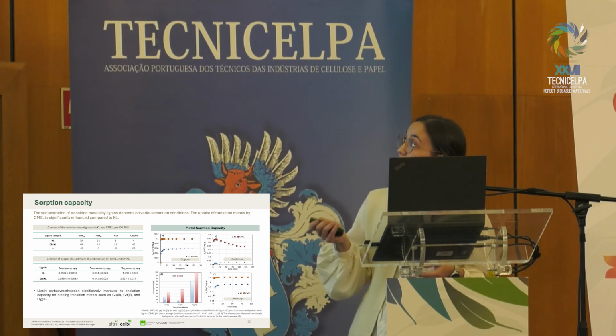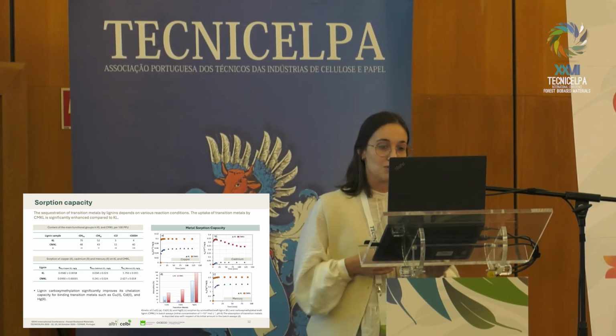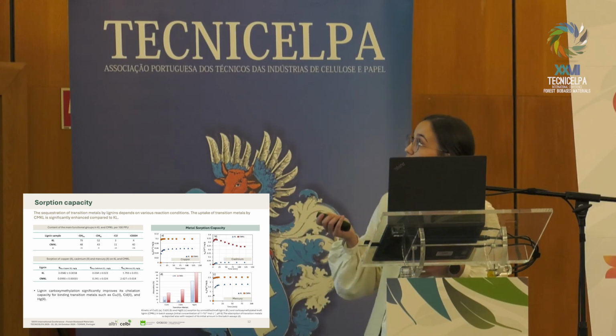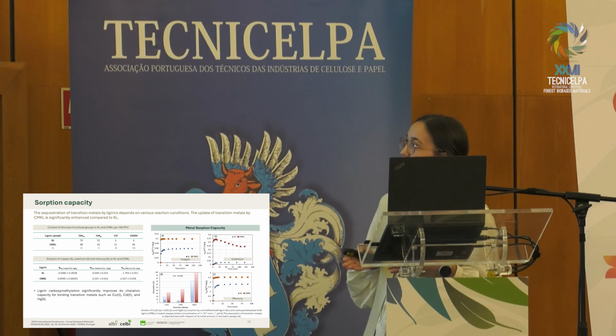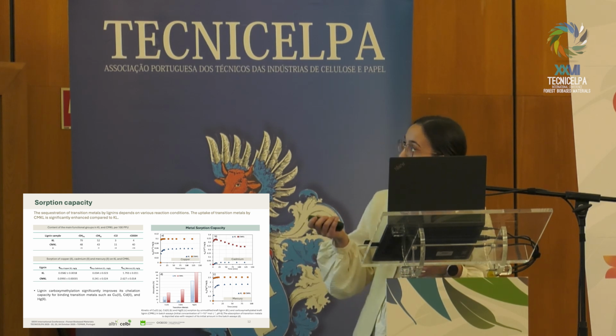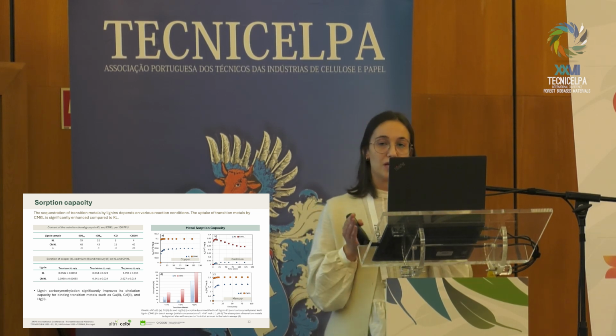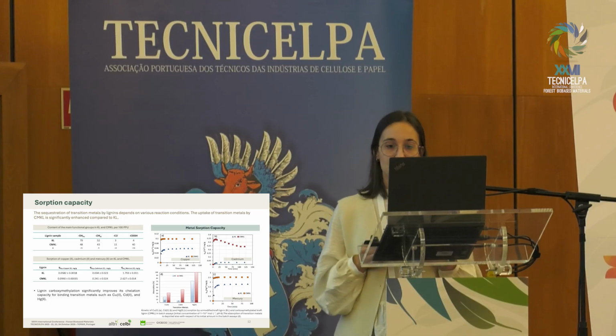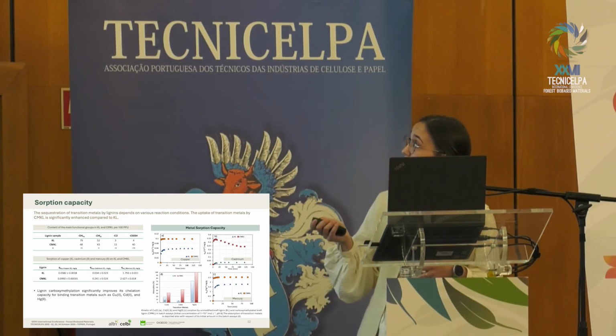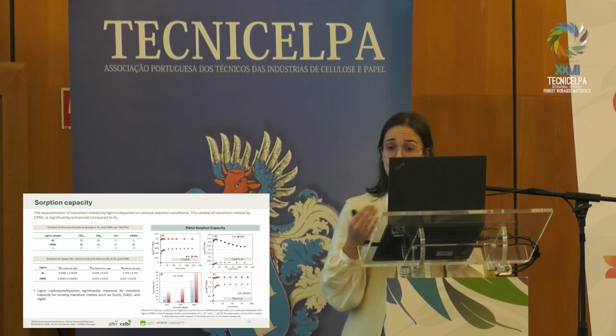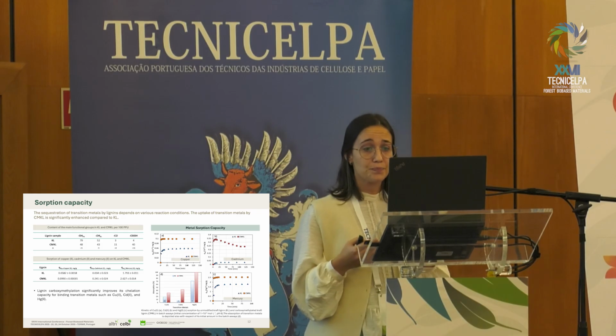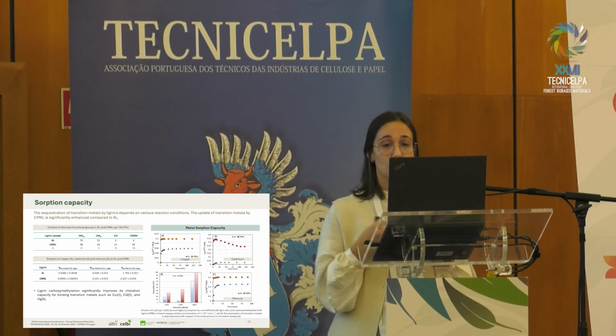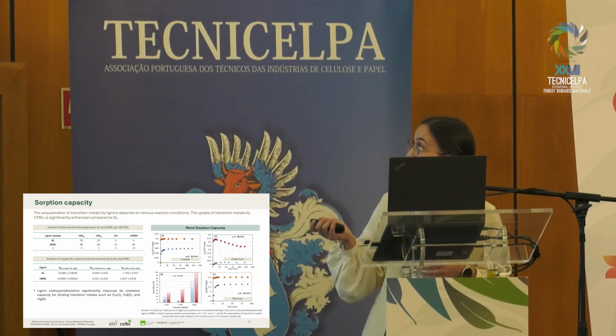We also performed thermogravimetric analysis of these two compounds. They have similar behavior, but the maximum degradation rate occurred for the modified lignin at a slightly lower temperature, more or less 50 degrees. And we also observed that the modified lignin shows high ash content. And this is due to the presence of carboxyl groups in the form of sodium salts.